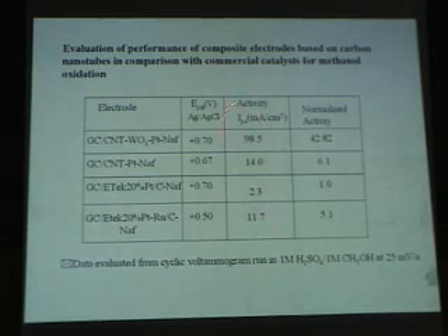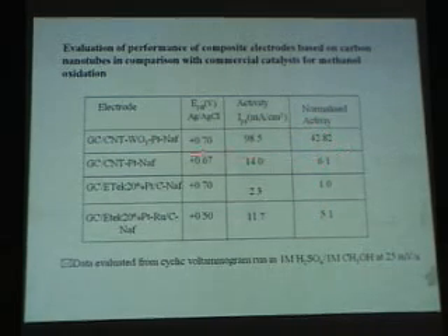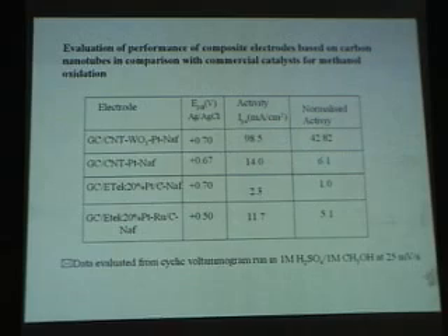Now, we forget about even this. You look at this. This is the commercially available electrode. It is of the order of 1. If the activity is assumed to be 1, we are now having an activity of the order of 50. If we had an activity of 300, as I told you, it is already commercially viable. Okay. This is platinum ruthenium commercial catalyst. This is the E-tech catalyst, which is being used in many of the fuel cells today. When compared to them, definitely our system has a higher activity. Next one please.